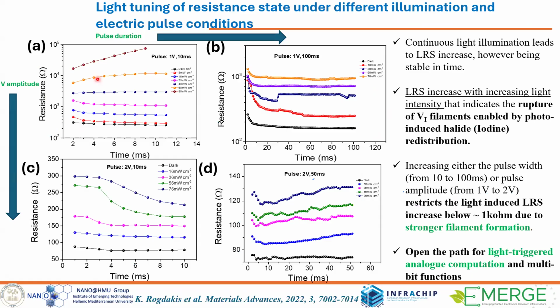We have demonstrated on the left here, we plot the resistance on time, plotted data in dark. So when we increase the light intensity from 0 up to some milliwatts per centimeter square, we can almost analog linearly tune the resistance of the device. So we can do this analog computing, let's say.